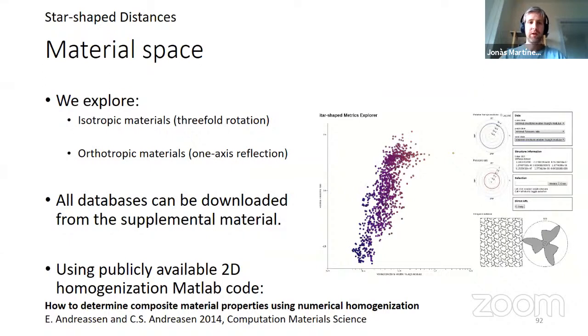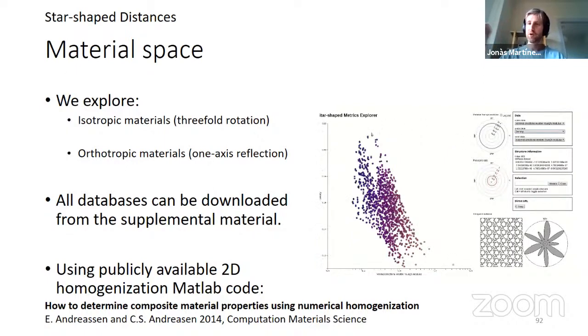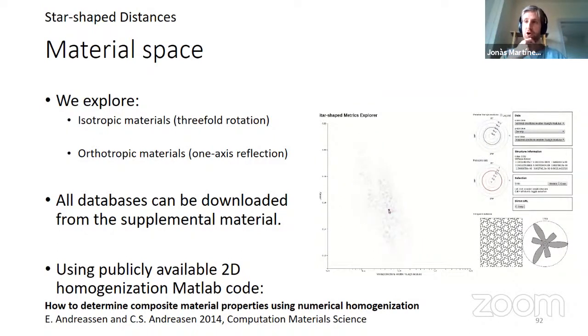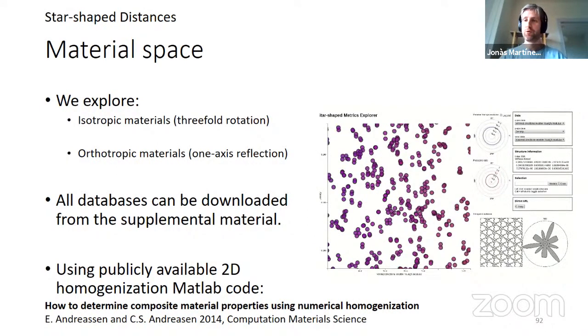So we have explored different combinations. In particular, we explored the threefold rotation, which corresponds to isotropic materials, and one-axis reflection, which corresponds to orthotropic. And you can download the databases from the supplemental material in the ACM library. You will have this kind of HTML database where you can navigate and see your structure and the corresponding distance. And we did the homogenization with publicly available code. And I think it's not here, but the code to compute the Voronoi networks is also completely open source. So you can replicate some of the results in the article.